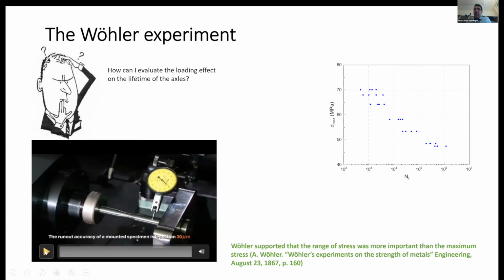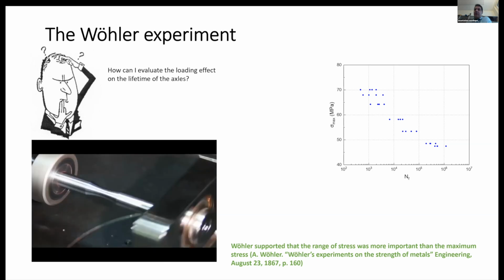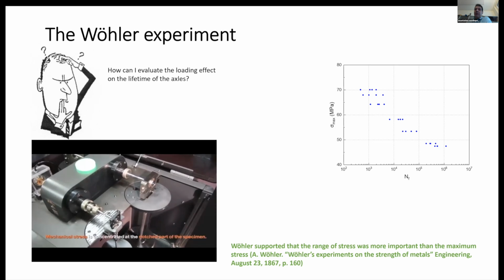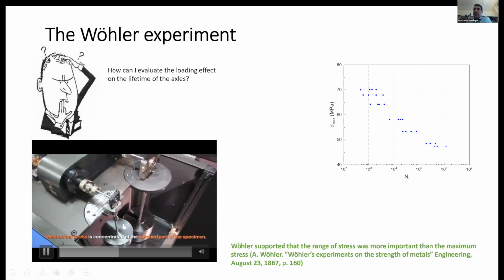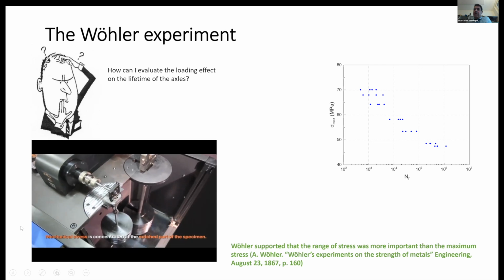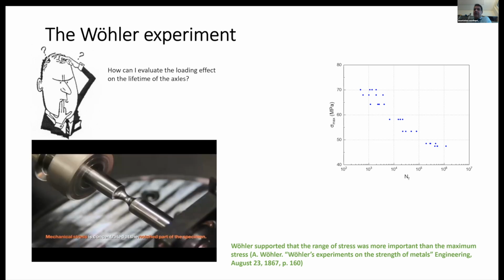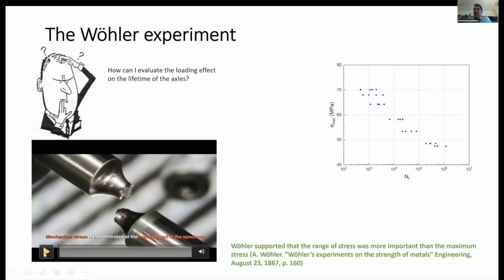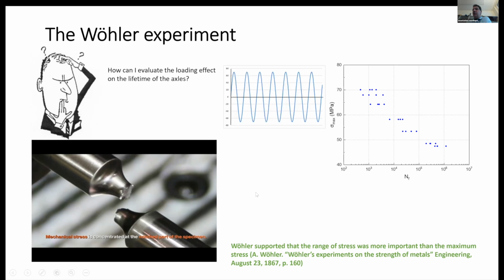So a typical example of what he did, but today's example is this one. We rotate the structure, the material, it's this one here. We rotate it, and we have a load down there. And then at a certain moment, the material fails. And when it fails, we measure the number of cycles at failure and we put it here. So we know the stress, we know the number of cycles at failure. And then we ask, how can I evaluate the loading effect on the lifetime of the axle? This is exactly the way to do it.